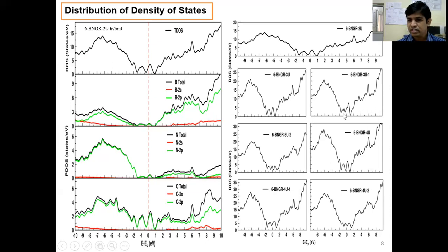With vacancy there is a further shift, and with double vacancy there is no touch to the x-axis, meaning the ground state energy of electrons is enhanced because of the vacancy. Similar things are also observed with 4-layer hybrid layers. By increasing the width, the lower energy states of electrons are enhanced.